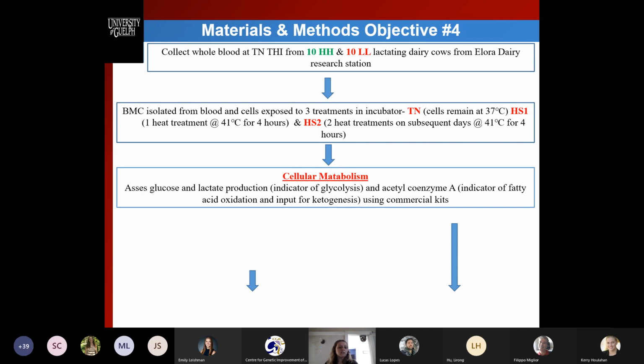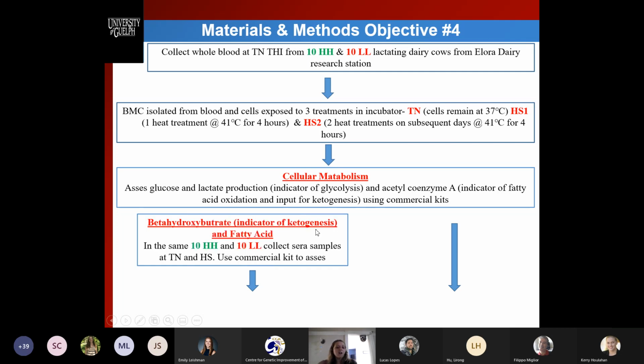So we looked at glucose and lactate as an indicator of glycolysis, as well as acetyl coenzyme A as an indicator of fatty acid oxidation, which is also an input for ketogenesis. We did this using commercial kits. Additionally, we looked at these 10 high and 10 low cows, but collected sera from them at thermoneutral and heat stress times to assess beta hydroxybutyrate and fatty acid concentration.